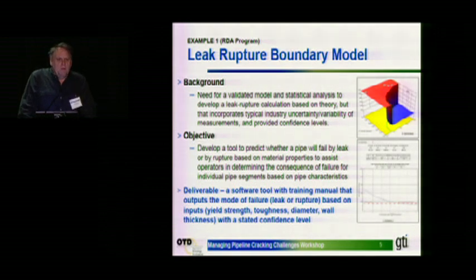We were able to get hold of about 20,000 data points from 14 countries, 4 different continents, over a 40-year time frame, where people reported ruptures of pipelines. And we did a very extensive quality control on those, and we came up with 635 data points which we were very sure of.